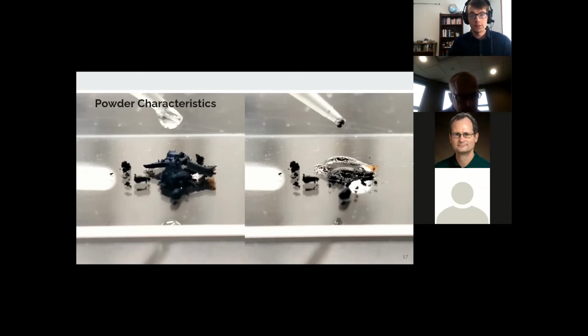Directly out of the synthesis system, the powder is expanded about 10 times from wetted aggregated packed spheres. And to see it visually, a small amount of solvent was added to a sampling of powder, as pictured here. The powder goes into solution and dries in a much more densely packed form as the solvent evaporates. So this image shows 1 milligram of powder, which was wetted with about 10 microliters of alcohol solvent.